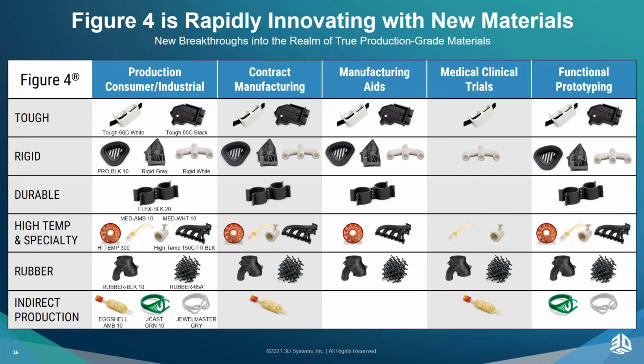In fact, the gray materials you can see start to fade. That is, again, one of the things we look at in this long-term stability testing, and we probably don't talk about the black enough because it never changes. We don't see the black material fading in this type of testing when we go through and look at this accelerated testing. The rigid grays have a tendency to turn green and brown over time, and these particular materials do not. They hold their color stability, as you saw on the previous slide, where we were out at 8 years, and the part looks exactly like it did when it started the accelerated testing. So great question.